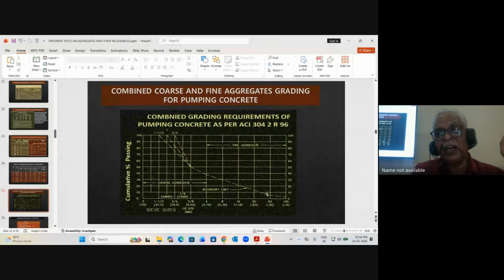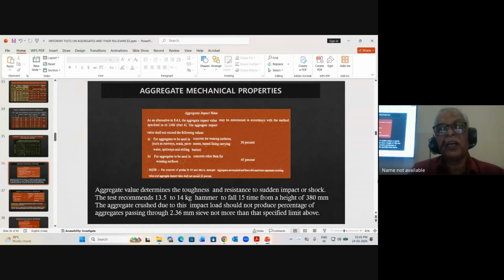This is the combined grading aggregate, this is the boundary line. Up to 10 mm there's not much difference, but after 10 mm it expects the same percentage passing. So this is how we can design the concrete mixes also. Of course IS code gives a different method, but I feel this is more relevant than IS standard. This can be thought of. This ACI standard you can note - ACI 304.2R96, very interesting code. Of course, aggregate impact value...